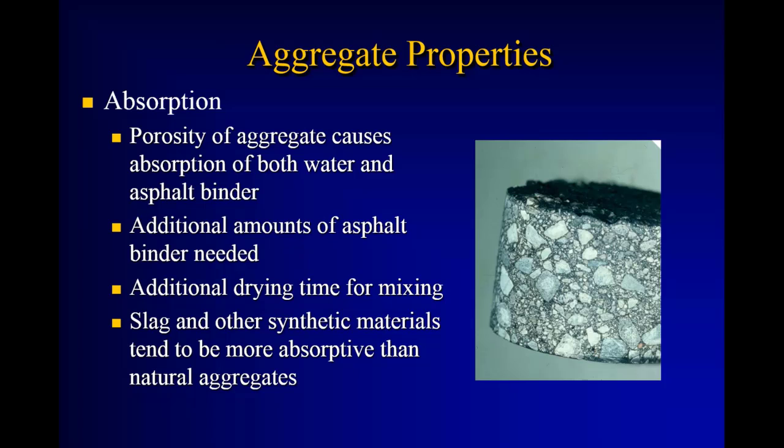And we can run a lab test to determine the bulk specific gravity, apparent specific gravity, and the water absorption of aggregates. If we know the water absorption, basically we can thumbnail the asphalt absorption. If our water absorption is 2%, the asphalt absorption is probably going to be around 1%. Asphalt's a lot bigger molecule, so it won't penetrate into those water permeable pores as far as water will.